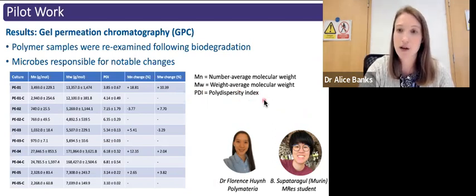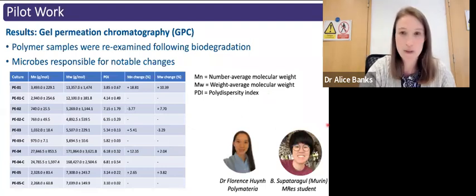And this is a metric which indicates the heterogeneity of the sample. So a higher index suggests that there was a larger range of particle size, whereas a small number suggests that the particles were all fairly similar to one another. So I'm just going to point out a couple of examples in here. And if we look at polyethylene sample 1, this was one of the polymers that led to good microbial growth.